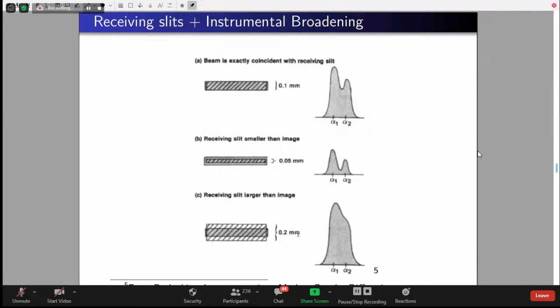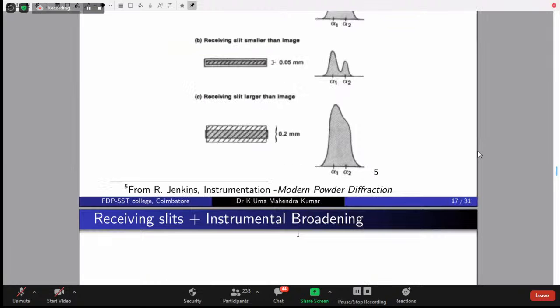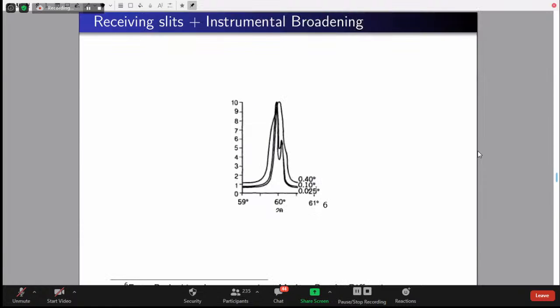So all of them, you can see they are at different angles. You can't figure it out. If you plot them together, you can see here, instead of width, it has been given in angles. You have a smaller angle and larger angle. So when the angle is large, you will have a broad peak. It is just because of the receiving slit. It has got nothing to do with your crystallite size. So we have to choose the right experimental setup in order to get the right data and our interpretation further.